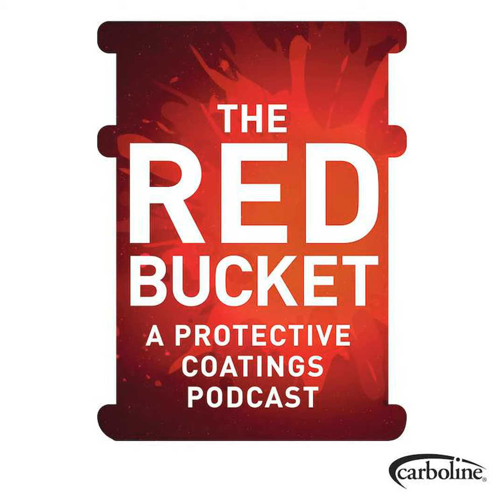Correct. So when the previous lining is removed, now it goes into the mechanical process where they'll inspect the thickness of the tank shell, and then they'll start grinding and blending of those areas that need to be built back up by the welding process. But that's a lot of square footage. You're talking about 1,000 to 1,100 square feet of steel, right? There are some areas that might be missed, and it might be more of an omega pitting, what I call. So those are very challenging for a coating.